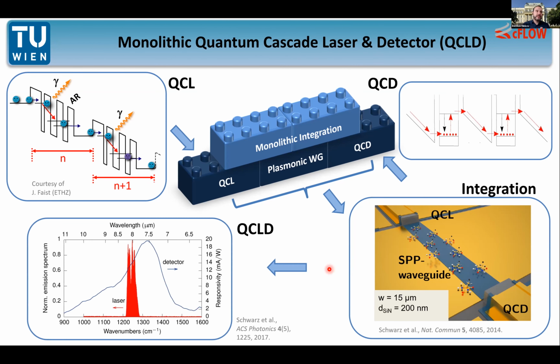One thing I want to stress, because this is important, is that the laser and detector are from the same active region material, and they are optimized so that the laser emission and the detector sensitivity or responsivity are matching as well as possible. And you see, they overlap very nicely. Therefore, we can really use the same active material for emission and for sensing, and make such small and compact on-chip devices.